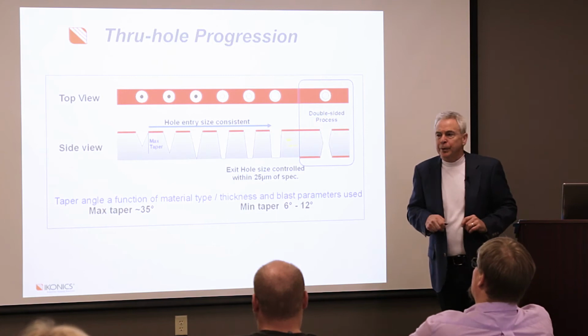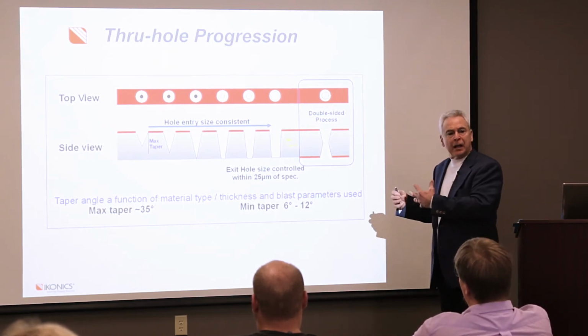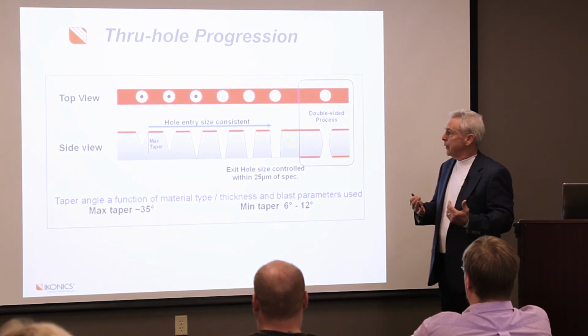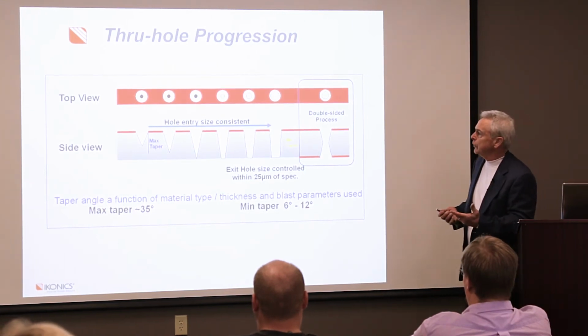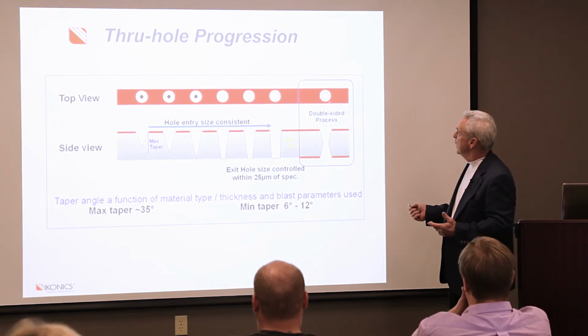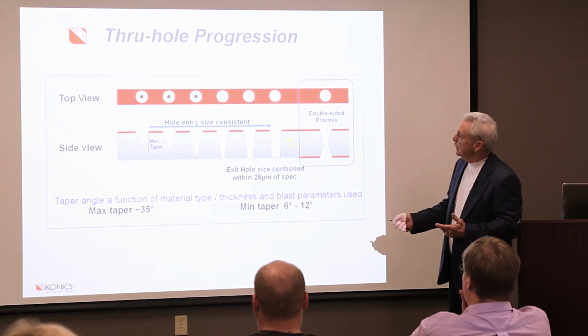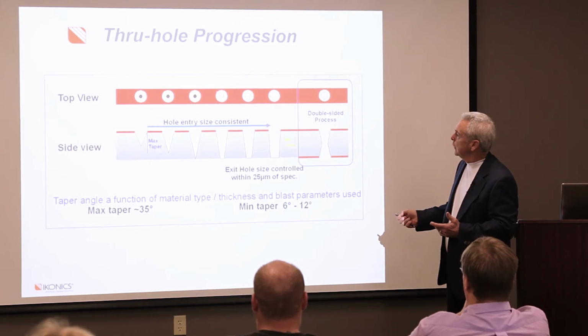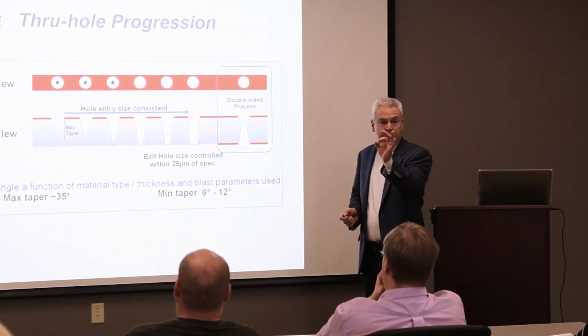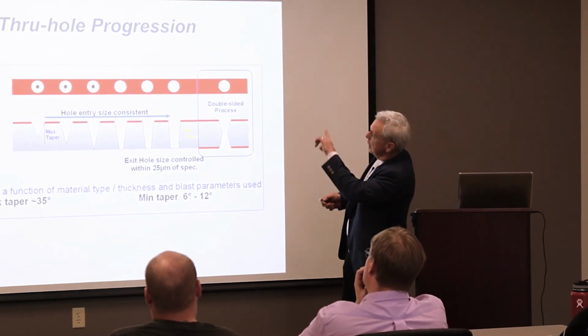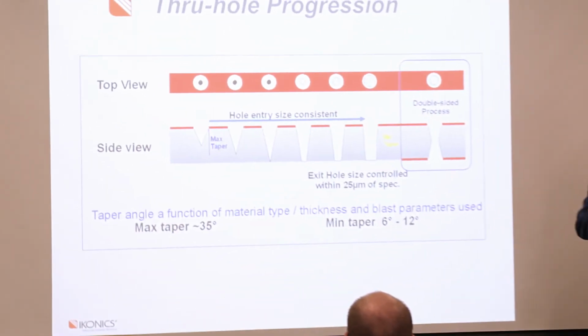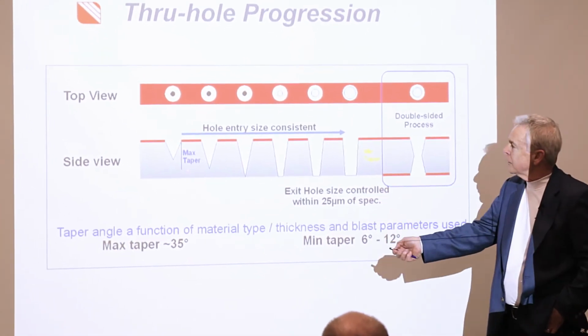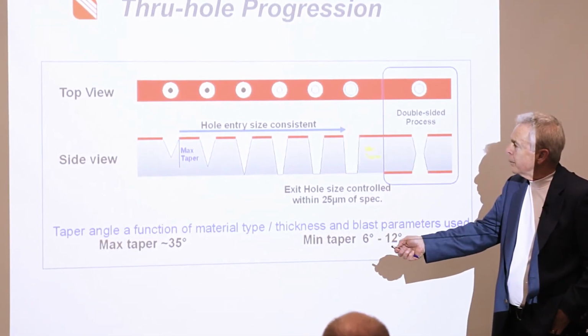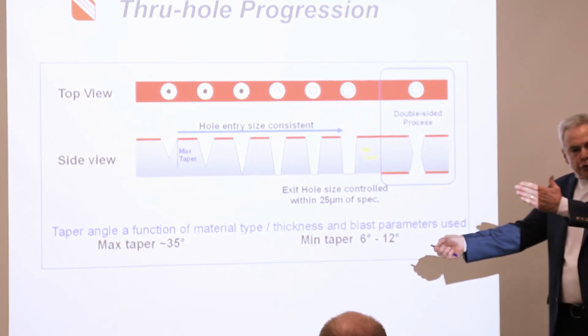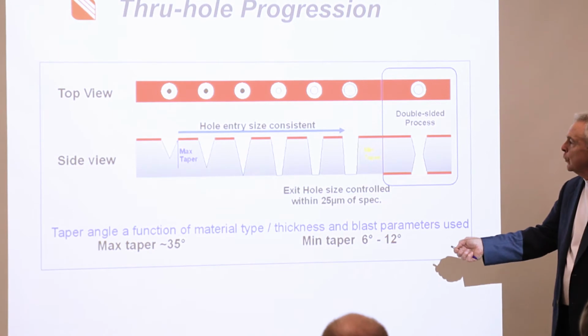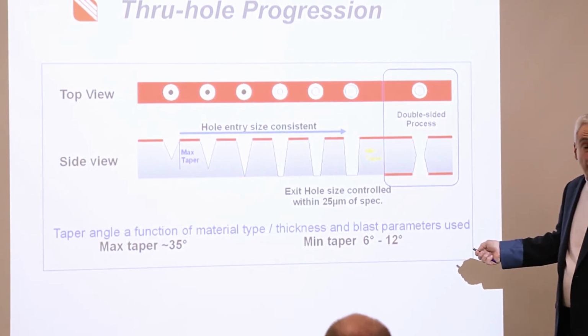Now this chart's a little busy, but let me take you through it because it really explains how the process works and why we end up with so few stresses or damage to the material. What you're looking at here is a top view where the mask has been applied to the substrate, and the red is the mask, and it's been imaged so that you see the round opening, which is the same size for each of the holes in this particular case. Taking that and looking at a side view, the way the process works is as you start to blast, you start to erode away at the composite material, and the more passes that you do back and forth, the more that material gets eroded away and eventually comes all the way through the bottom.